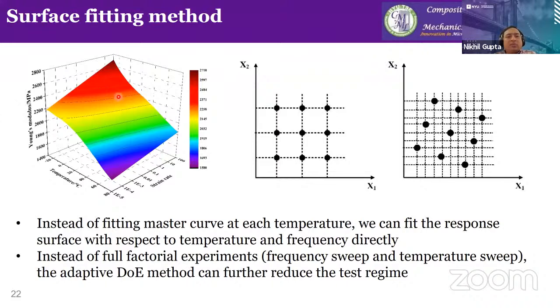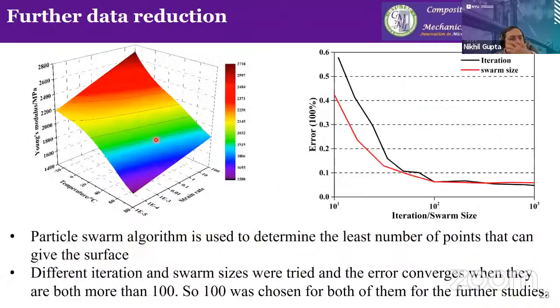So you can start with maybe 3 points to start with, and then you keep adding points until you are able to capture this surface with a good quality of fit here. So in this case, with the particle swarm algorithm, which is the simplest one, what you can see here is that about 100 points give you pretty good convergence. The error is below 0.1% in that case.